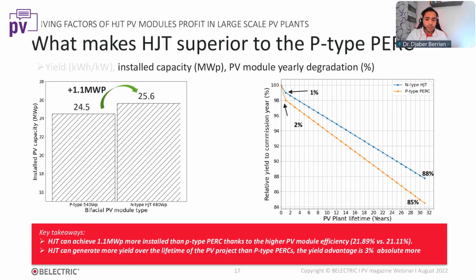What you see here is the degradation over time of the power plant for both PV modules: the P-type PERC in orange, and the N-type heterojunction in blue. Importantly, in the first year degradation for the P-type is 2%, while for heterojunction it is only 1%. And over the years, the P-type degrades faster than the N-type, which makes quite a big difference. At year 30, you get 3% more for the heterojunction PV module.